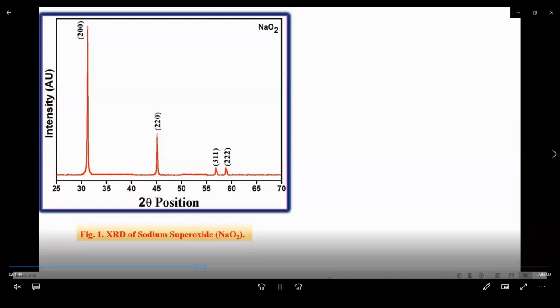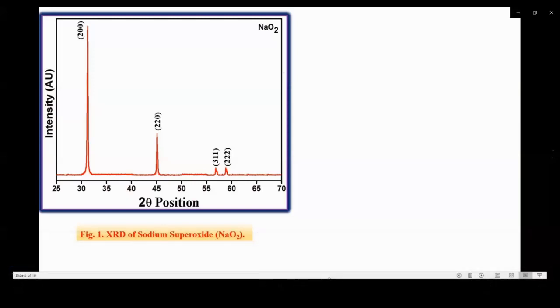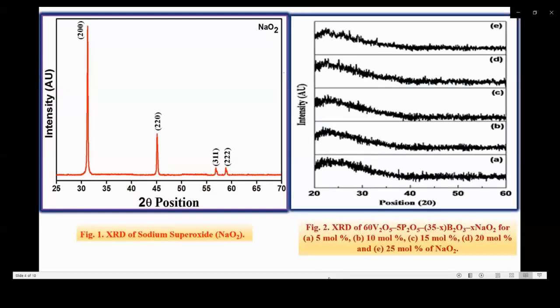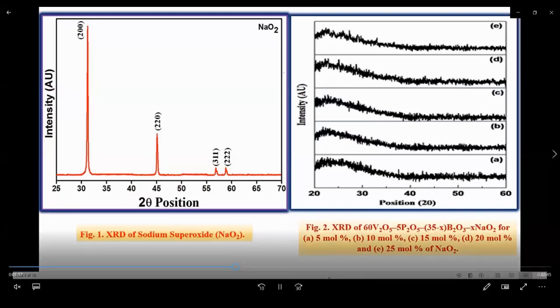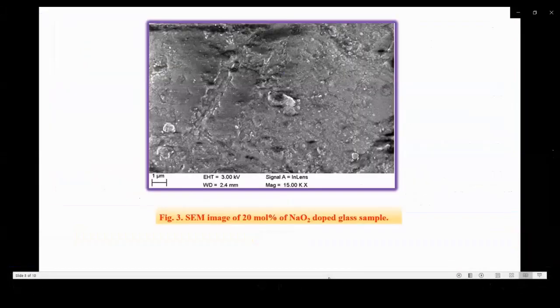Figure one shows the XRD of sodium superoxide. The four peak positions appearing in the pattern exactly match sodium superoxide according to the JCPDS data. This figure shows the XRD pattern of the prepared glass sample. As there were no characteristic peaks corresponding to any crystalline phase, this confirms the formation of glass. This is the SEM image of the glass sample. From this, it is clear that the sample exhibits irregular granular morphology.